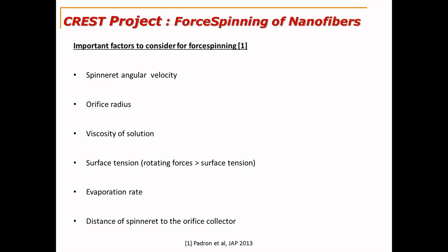And the surface tension also plays an important role. Coming to the evaporation rate, we are spinning fibers from polymer solutions here. That means we are mixing polymer with some kind of solvent, so the solvent evaporation rate plays an important role. If the solvent evaporates too quickly, the polymer solidifies before reaching the collector plate and will not be deposited properly on the collector plates. If the solvent evaporation rate is too low, it may cause beads while forming the fibers.